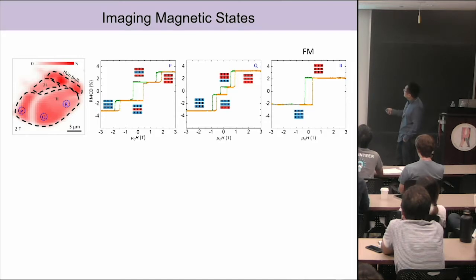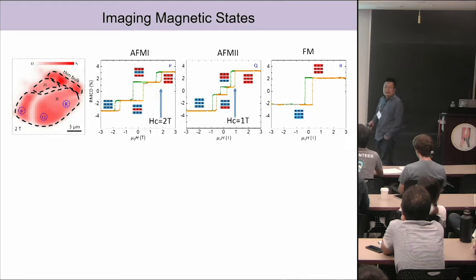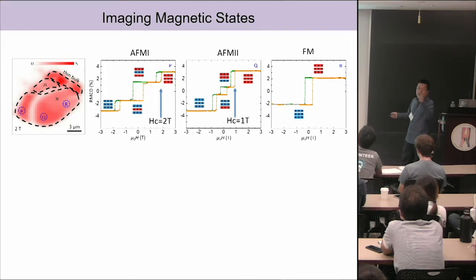And we find these two, one is AFM1, the other AFM2. The way to do it is very simple, as I already mentioned to you. Just look at the magnetic field that we need to realize this spin flip transition. For the AFM2, only one interface is antiferromagnetic. For the AFM1, there are two interfaces. Therefore, the field we need for AFM1 for this spin flip transition should be twice that for AFM2. So that's what we see. For AFM1, we need 2 Tesla. For AFM2, we only need 1 Tesla. So that's how we can tell we do have these two different states.